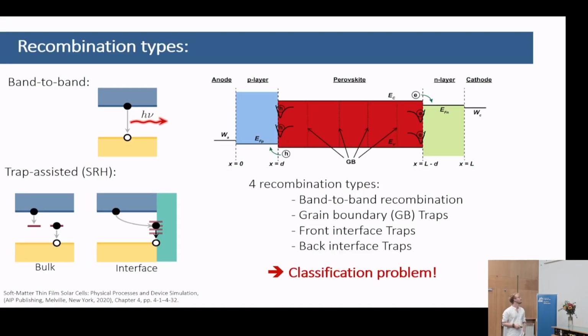perovskite. And basically, when you think about this, it's really almost a simple classification problem, right? You have different possibilities. It can be band-to-band limited, bimolecular, if you prefer organic terms. It can be limited by grain boundary recombination, by the front interface recombination, by the back interface. And the goal really is to try to pinpoint that without having to do any extra measurement than light intensity dependence.